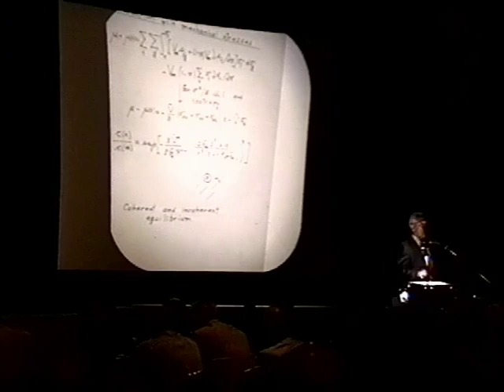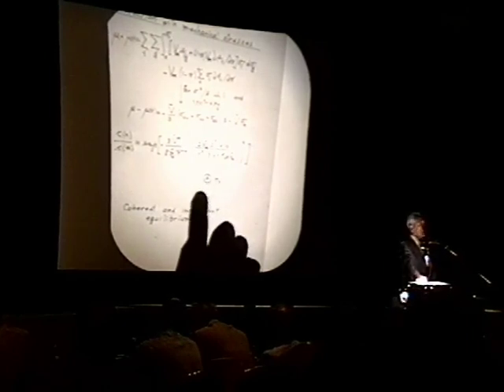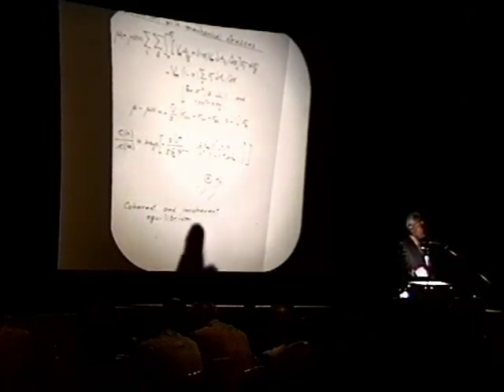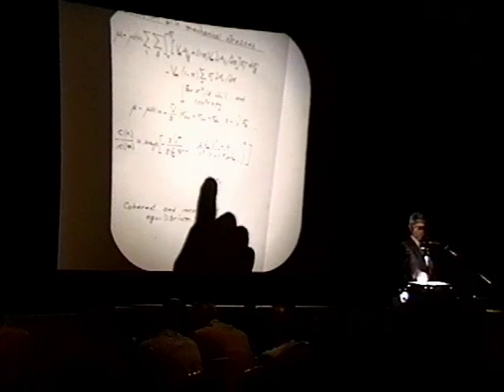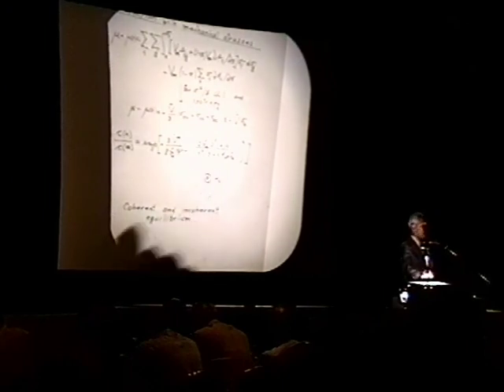This gives rise to two kinds of phase diagrams in systems such as the metal hydrogen system, the coherent and the incoherent phase diagrams. The coherent phase diagram results in a truly thermodynamic equilibrium between one phase and the other. They are sharing the solute at the same chemical potential equilibrium, but by virtue of the stresses, the mutual distribution between the alpha and beta phase is different from what happens when the beta phase breaks away from coherency by nucleating dislocations at that interface and emission of those dislocations to the grain boundaries and the external surface.